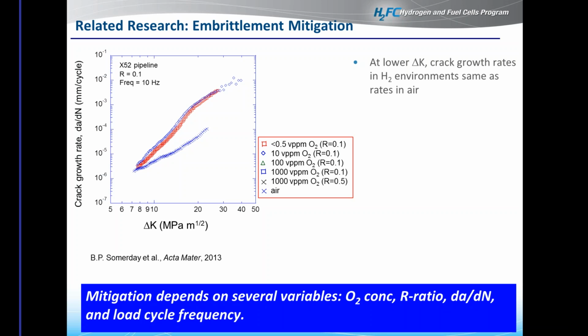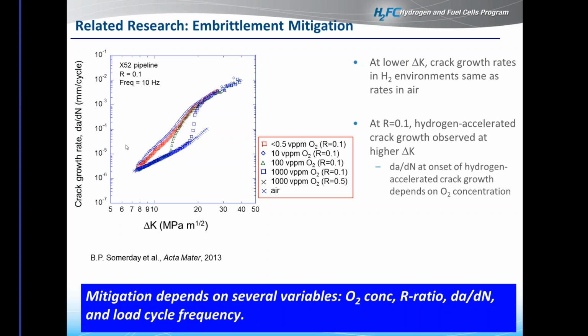But when we look at 100 ppm, what you'll see is that the curve actually follows the data in air up to a da/dN of approximately 10 to the minus 5 millimeters per cycle. And then we begin to see hydrogen accelerated fatigue crack growth occurring, and it converges with the other curves. As we move to a higher oxygen content of 1,000 ppm, what we see is that the da/dN at which the hydrogen accelerated fatigue crack growth occurs is pushed to a higher value.